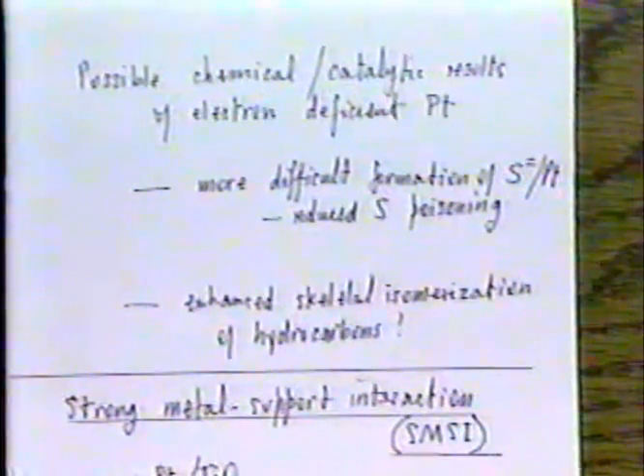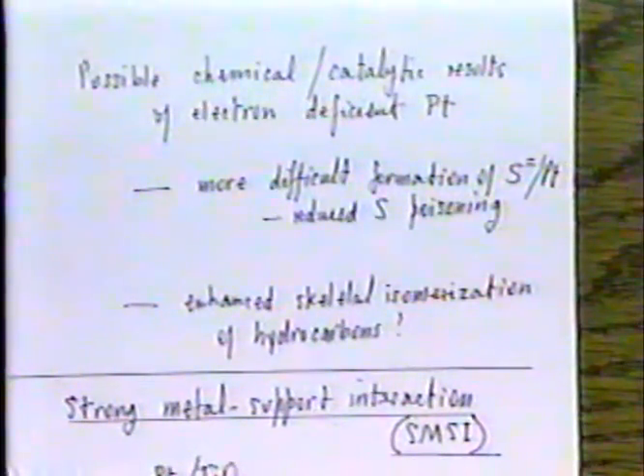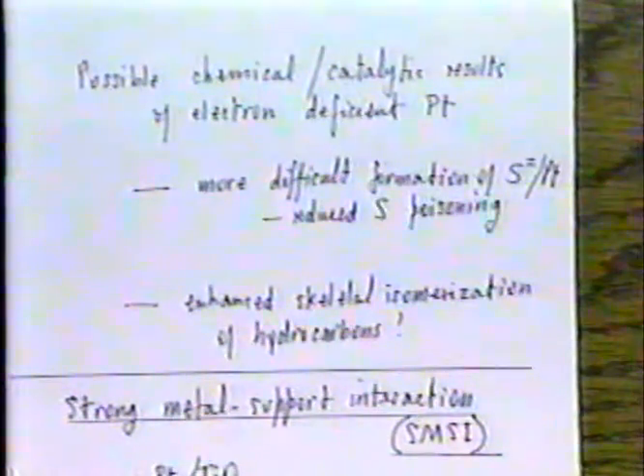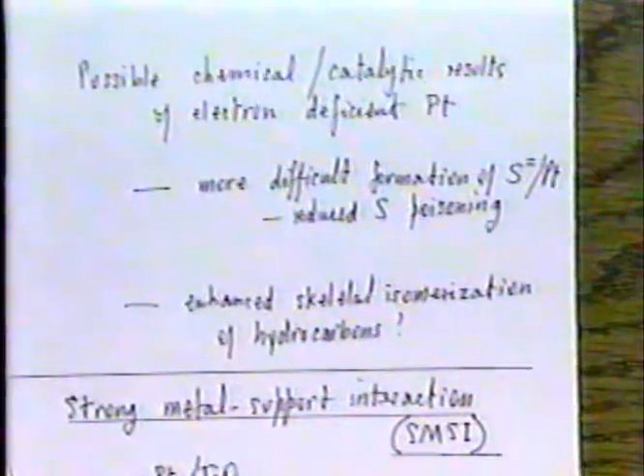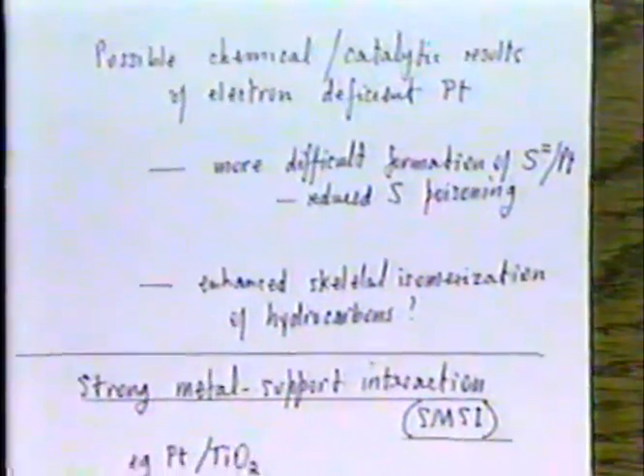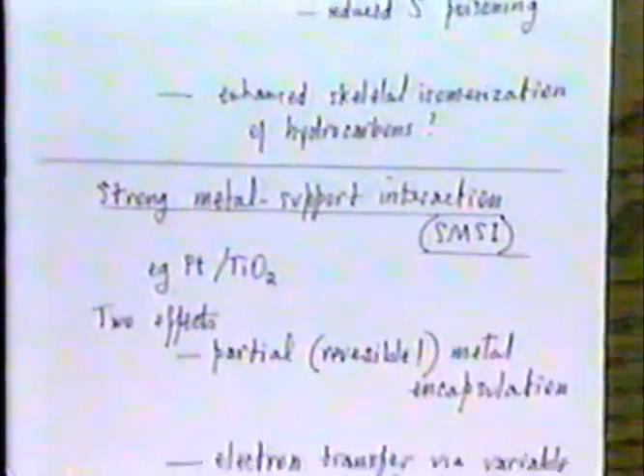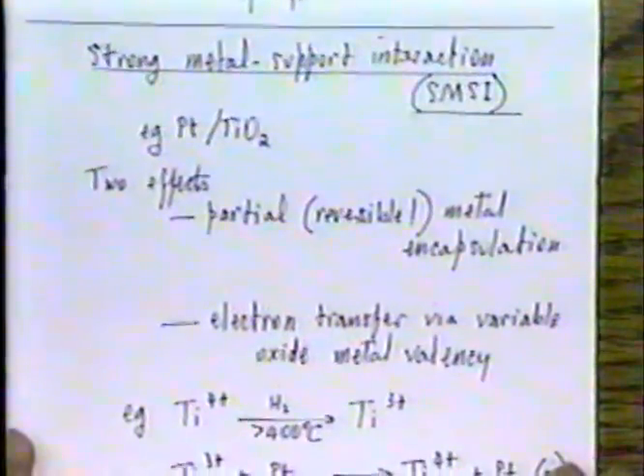That's one thing. And the second thing, which we'll briefly return to later on, is the fact that when you have electron deficient platinum, or platinum from which it's more difficult to obtain electrons, there is an increased propensity for hydrocarbon skeletal isomerization, and we will have a little bit to say about that later on. But before leaving this, I want to turn to just say something about strong metal support interactions.